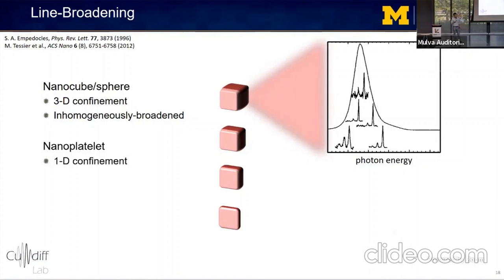In nanoplatelets, the situation is quite different. So in nanoplatelets, excitons experience dominant one-dimensional quantum confinement. And because the thickness of these nanoplatelets can be controlled very accurately down to single unit cells, this dramatically reduces inhomogeneous broadening to the point where it's often claimed that spectral line shapes in these nanoplatelets are homogeneously broadened.